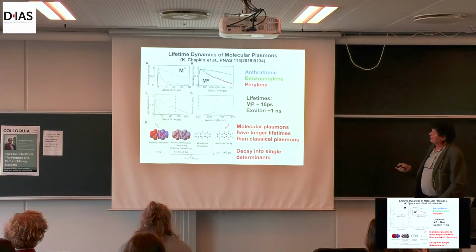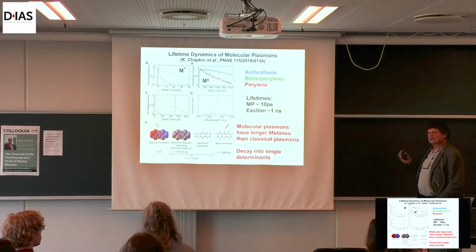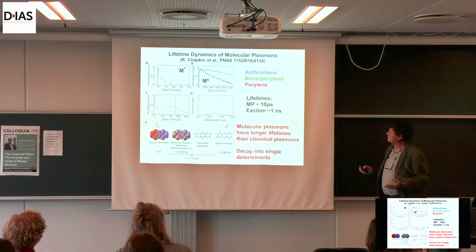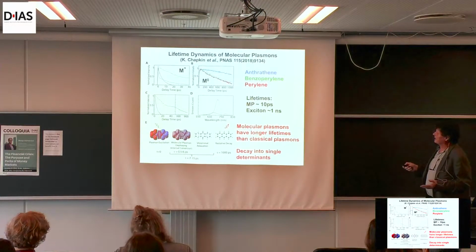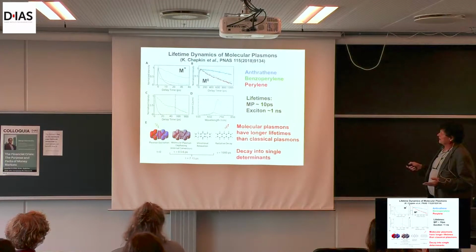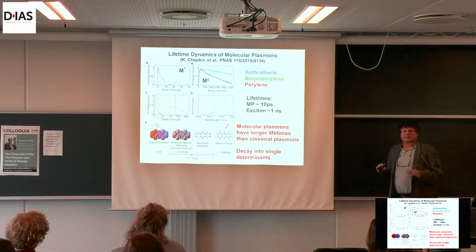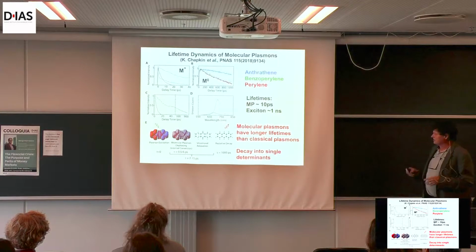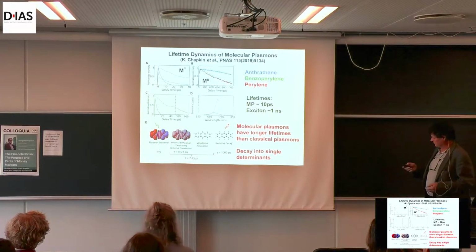And we recently published an interesting investigation on the lifetime of these molecular plasmons. What we show here is that the lifetimes of molecular plasmons are actually longer than typical plasmons. It's about 10 picoseconds. So it's a pretty stable system.